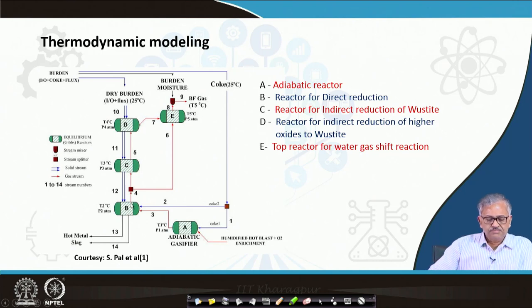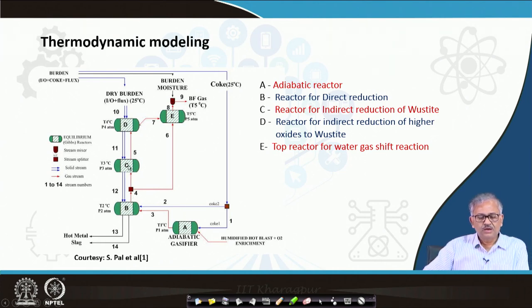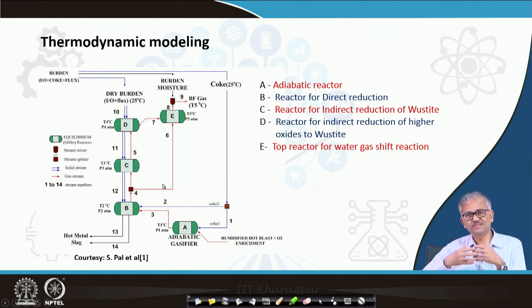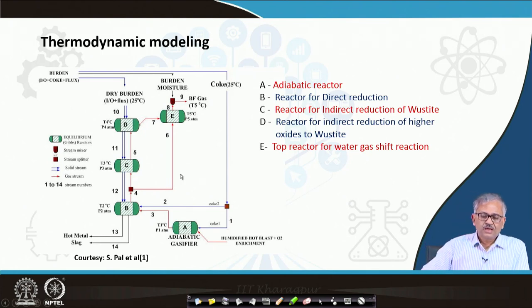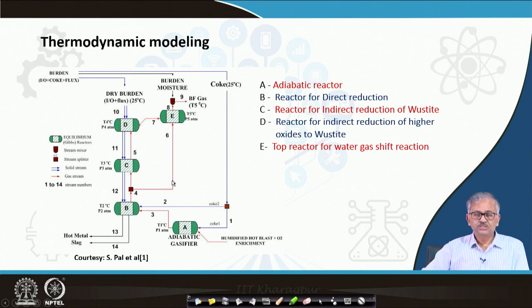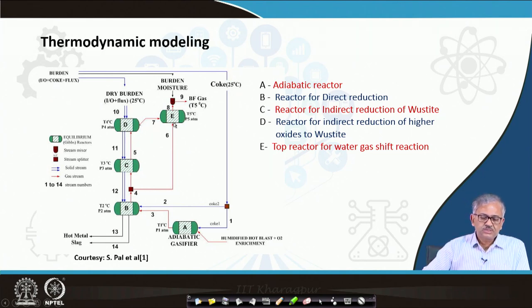Finally, this gas stream — now you have CO and CO₂, no more pure CO — will come and enter reactor C. Reactor C is a reactor for indirect reduction of wüstite. Whatever gas is coming and splitting, a part is going directly to reactor E, which is basically the final gas composition reactor. This CO will not participate in indirect reduction because of kinetic considerations. A part of CO is taken off, calculated based on the shaft efficiency of the blast furnace — that is the CO utilization — from which you can estimate how much to take out.